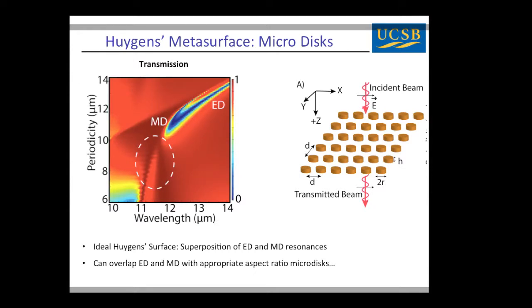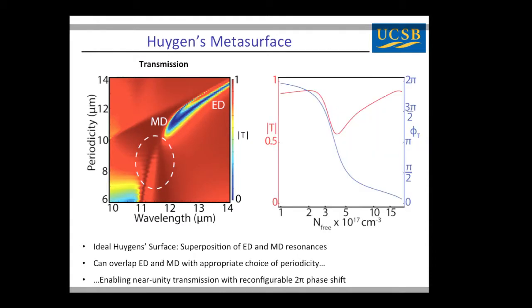So if you use the right aspect ratio disk, what you see is that now I'm plotting transmission as a function of periodicity and wavelength. And what you see is that there's a large region of parameter space where the transmission is unity. Okay, so now we can operate near this region and look at what happens as we introduce free carriers. And the key result here is our blue curve, which is that the phase evolves over 2 pi. Okay, so by introducing free carriers on the order of up to 10 to the 18 per centimeter cubed, we can get a 2 pi phase shift in our array. The transmission is not strictly unity everywhere, but we have less than about 2 dB of change in transmission. Okay, so it's not perfect, but it's a good start because no one in the community has really figured out how to get these 2 pi phase shifts in a reconfigurable fashion.